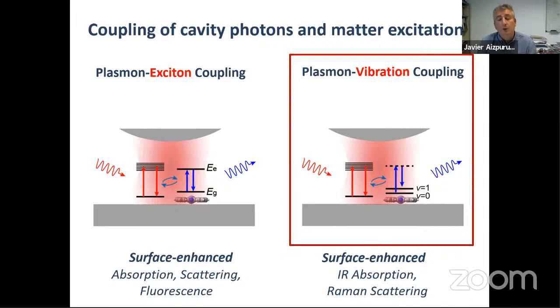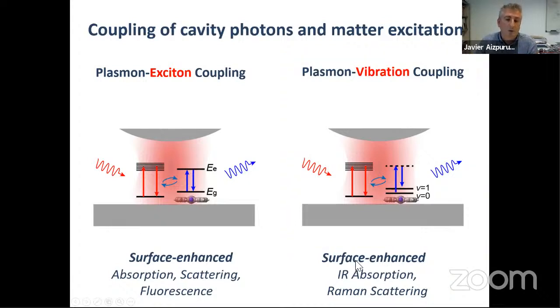Then with time, we knew that what was produced in the metals mainly were these plasmonic enhancements, this collective oscillation of the conduction electrons that were producing trapping in effective mode volumes and enhancement of the local fields. And that's why people kept talking about surface enhanced, even though now we could talk about plasmonic antenna enhanced or plasmonic junction enhanced or metallic nanoparticle enhanced, okay? So the reason to call it surface enhanced is purely historical. Now we could sophisticate it with the particular type of surface or nanoparticle or nanostructure we are studying, okay?